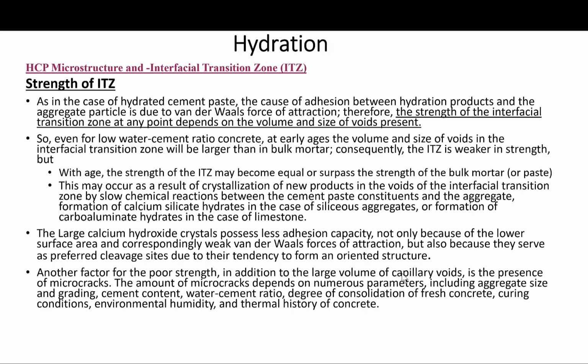So the strength of the interfacial transition zone at any point depends on the volume and size of the voids present. So even for low water cement ratio concrete at early ages, the volume and size of the voids in the interfacial zone will be larger than in the bulk mortar. Consequently, this will be weaker in strength.